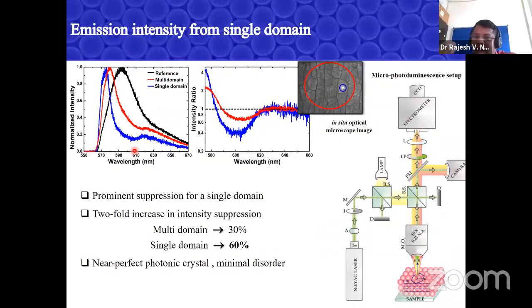So this is the way the spontaneous emission intensity is changed. The intensity is, in fact, suppressed at the frequency gap. We made the sample in such a way that the frequency gap coincides here. And if I take the ratio between the blue divided by black, or the red divided by black, and this is the way we represent data in this field, we can see that there is an intensity suppression.